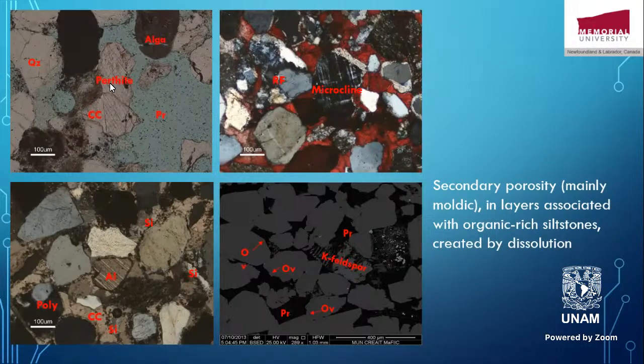This is some algae here, some perthite, and you see here some pore, a big pore here, also here, and microcline here, something like this. So it's all the components that we talked about. And here we see a backscatter diagram that shows some of the components of the sandstones. It also shows the secondary pores, as you see here. PR means a pore, so lots of pores there, and it's obvious that these were secondary pores developed by dissolution of the carbonate cement that precipitated earlier.